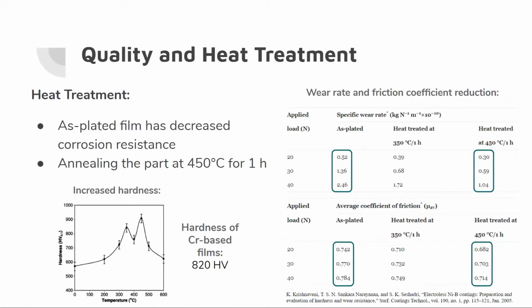Thanks, Linda. So now that we have the as-plated nickel-boron composite, studies have shown that it has a superior tribological performance. However, its corrosion resistance will be decreased. In addition, it has an amorphous structure, which can be made crystalline by doing heat treatment on the part at 450 degrees for 1 hour.